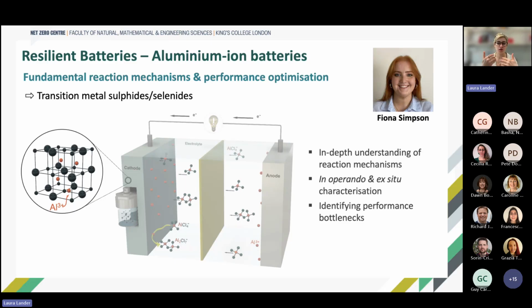We use a lot of operando and ex situ characterization techniques, such as operando X-ray diffraction or X-ray absorption spectroscopy, to really understand, for example, how our materials evolve upon charge and discharge, so when we extract aluminium 3+ and intercalate it, and also to understand where our performance bottlenecks are, how our materials change, how our materials degrade, where the issues are that we need to tackle, and how we can improve our materials, specifically the cathode material, in order to overcome those bottlenecks and to optimize the performance.